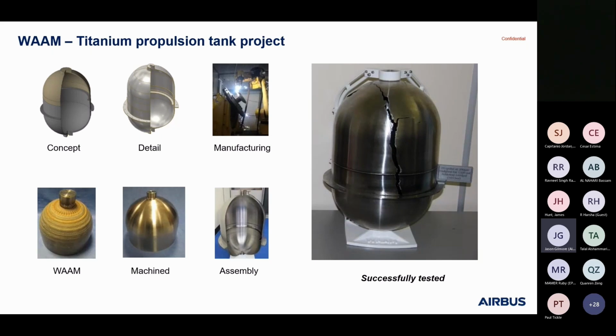So the actual failure mode, I hope you can see my cursor. At this junction here was the area of the highest microstrain. We've still got the strain gauges attached on the other side. And then the crack propagated upwards until the cross section got slightly thicker at the upper mount, and then took the path of least resistance. And at the same time, the crack grew downwards until it hit this external flange, and then the flapper material came away here and here. So that was the failure mode. The point being, very successful test and in line with the test predictions. If we can move on, please.